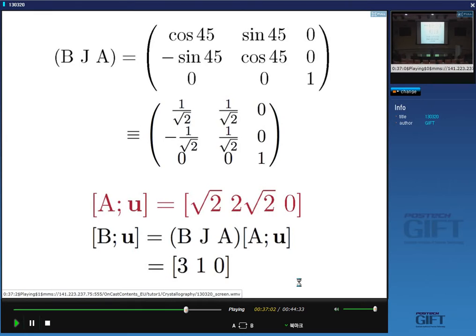But in the previous example, we had tetragonal and cubic. So the volumes of the cells were different in the previous example. Here the volumes are identical. So if you take a determinant of this matrix, it'll just come out as 1 because the volumes are identical. With the previous one, because it's a tetragonal cell and a cubic cell, they have different volumes. So the determinant will be the ratio of the volumes of those cells. Okay?